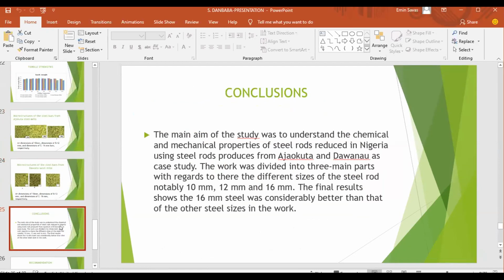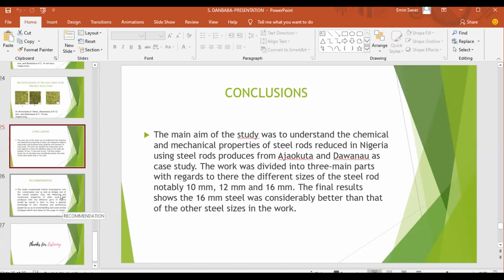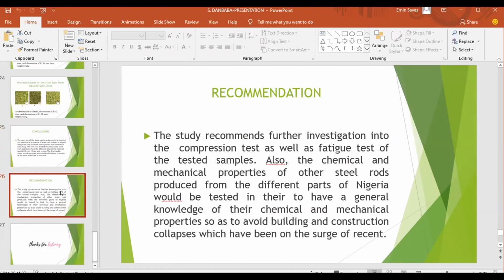As a conclusion, we compared the Ajaokuta and Dawanau steel bars for use as reinforcing bars for concrete. We find that some values are above the values listed in the standard. However, some values are below the values reported in the standards. So a further study is necessary. Compression tests and fatigue tests, for instance, should be done. And also the steel bars from the collapsed building should be investigated.